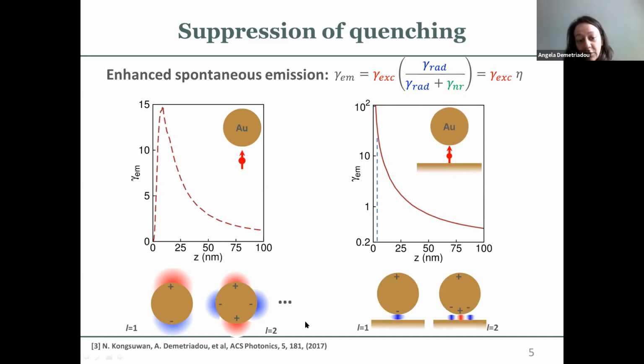And the reason for that is because you're confining this mode from the nanoparticle into the gap here. And if I'm standing very far away, where I'm detecting the emission from this system, this mode and this mode, they don't look too different. So basically, this mode now is allowed to emit to the far field. And because this acquires a radiative part, the energy that I couple to it doesn't get lost into ohmic losses completely, but part of it is radiated to the far field. And that's why I'm allowed to increase my emission rate that significantly, even if I'm just 1 nanometer or half a nanometer close to the surface of the nanoparticle.